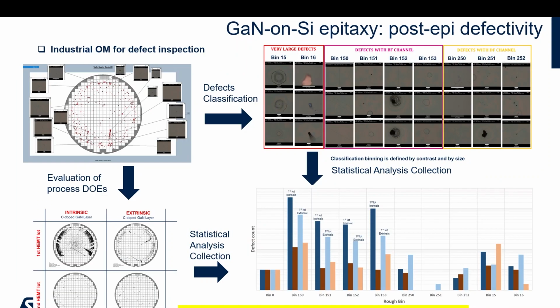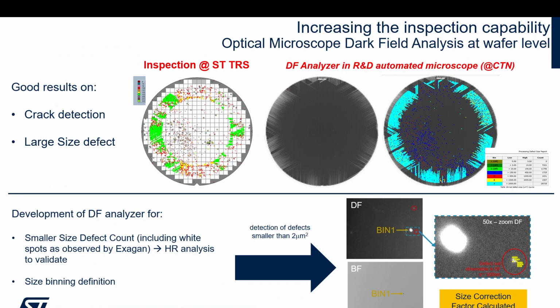And last but not least, you have of course to map defects, because there is no such process without defects. Defects can be cracks, can be areas of high stress, can be pits. You have to map each and every defect with dimensions that go, of course, to large dimensions like 20 or 30 micron, but also to very low dimensions, especially in the case of GaN. And you combine again optical and structural processes in order to have defined maps of this stuff. This is also completely different from what happens in silicon.